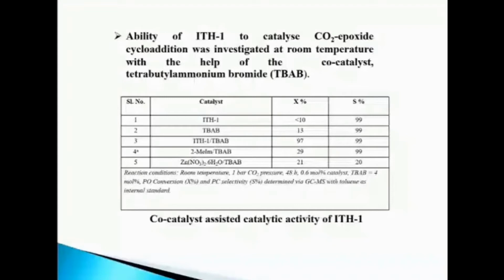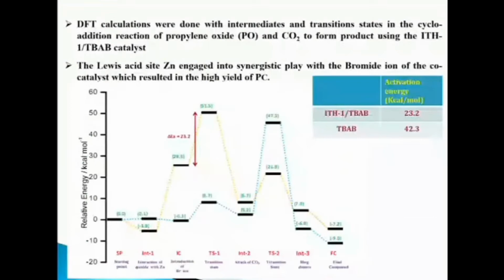For providing theoretical evidence, computational studies are also done. From this computational diagram, DFT calculation, the relative energy of ITH1 TBAB catalyst is taken as 0 as the starting point, which is indicated as the orange line. And the activation energy needed for this first transition state is 23.2. And the blue line indicates the co-catalyst TBAB alone, which needs 42.3 activation energy, which is almost double. Thus, from this diagram, we can observe that the Lewis acid zinc and NH group on the 2-methyl imidazole of ITH1 engaged in synergistic play with bromide ion of the co-catalyst, which resulted in high yield of propylene carbonate.